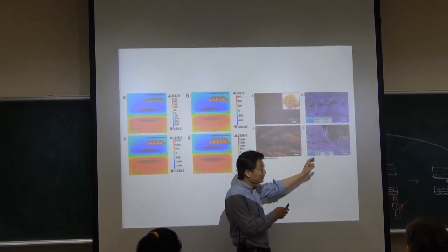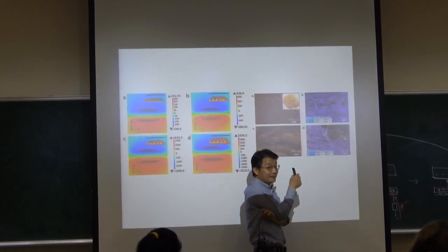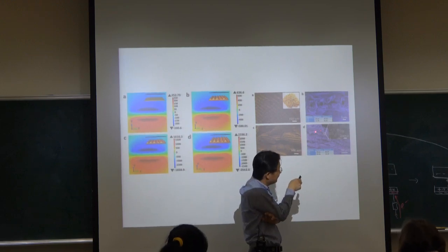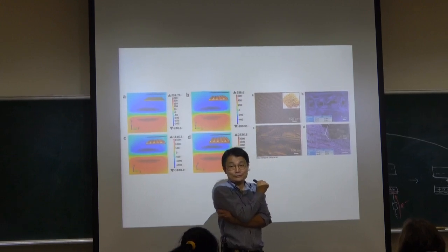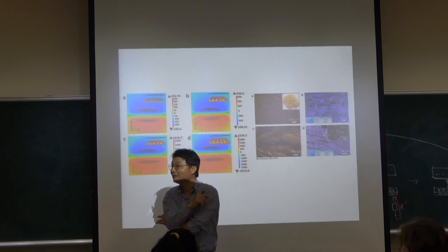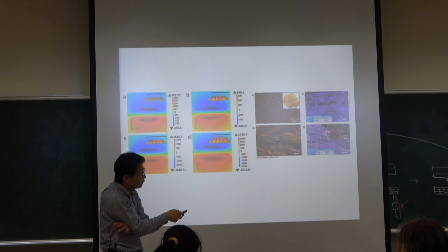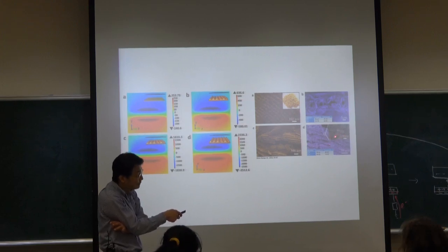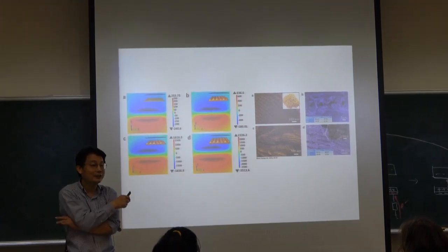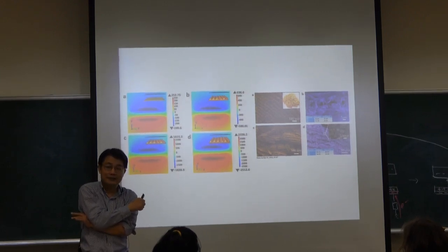Do you understand? So here is the raw material, the rice husk. Once you burn this rice husk, you will be left with SiO2, because the cellulose, the organic matter, will be burned out. If you look at this natural structure, it is mesoporous, just like the titanium dioxide. In the last chapter, chapter 6, we talked about titanium dioxide, mesoporous. Mesoporous is quite good.